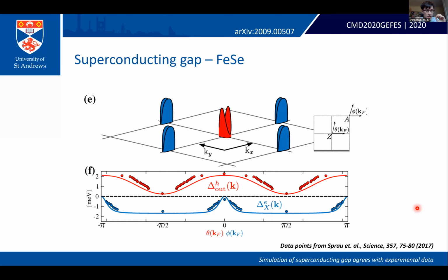Now, this is very exciting because there are theories of the nematic state which only involve xz and yz nematic ordering that have not been able to reproduce this momentum dependence purely from nematic ordering alone. And so this is really quite strong evidence that this dxy nematicity is an important contributor.